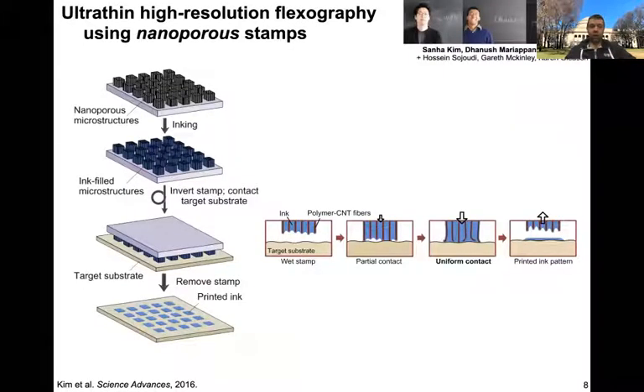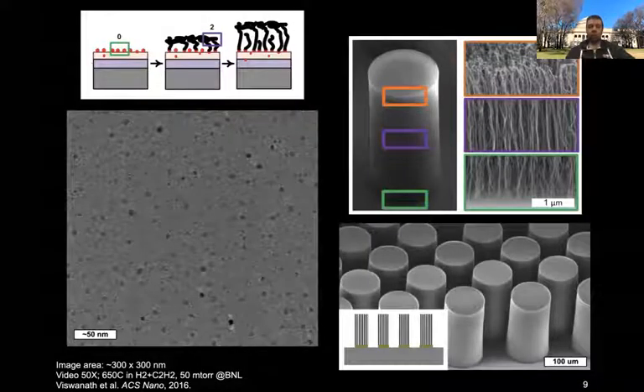So we had the idea that we could perhaps control this process better by using nanoporous stamps instead of non-porous polymer stamps. So there is the idea of using carbon nanotube-based stamps. And in a carbon nanotube-based stamp for flexography, you load the ink within the stamp volume because the stamp is nanoporous. And here's a simple schematic of how it goes. We, of course, make patterned CNT structures on a silicon wafer, and then we engineer them such that we can load them with a colloidal ink, and that allows them to be used in stamping. And therefore, we can transfer ink not from the surface of the stamp, or not just the surface, but from the volume of the stamp. And that turns out to be quite effective.